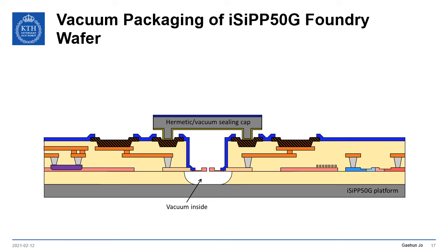The narrow sealing ring is designed to have a small sealing footprint and induce plastic deformation at the gold-aluminum interface due to high local pressure during the thermal compression bonding process. Additionally, the induced plastic deformation makes the transfer bonding process relatively insensitive to the roughness of the aluminum and gold contact interface, which simplifies fabrication and greatly improves reliability.